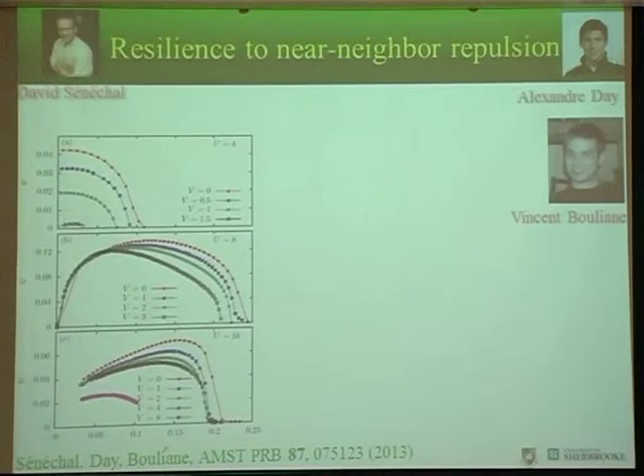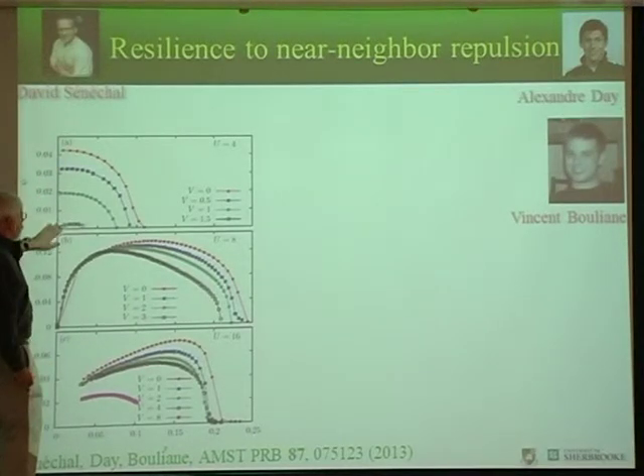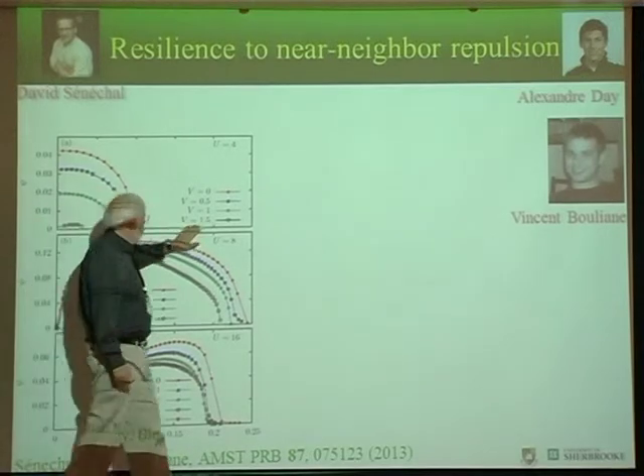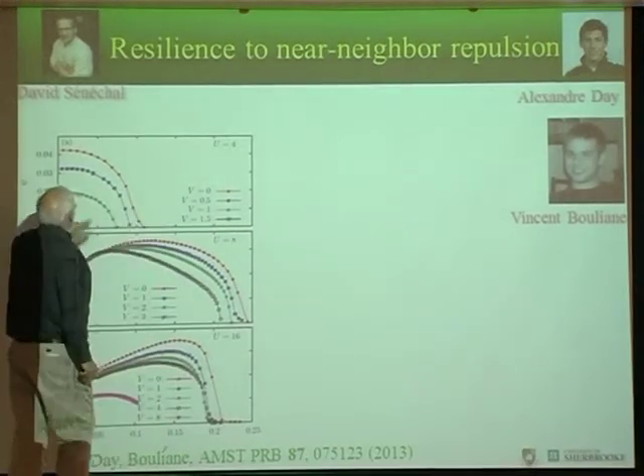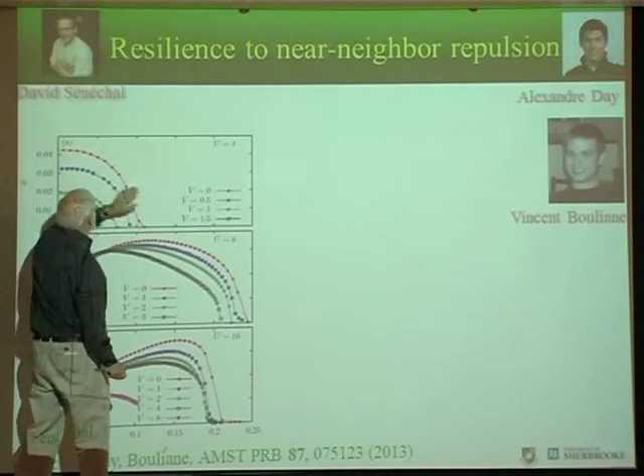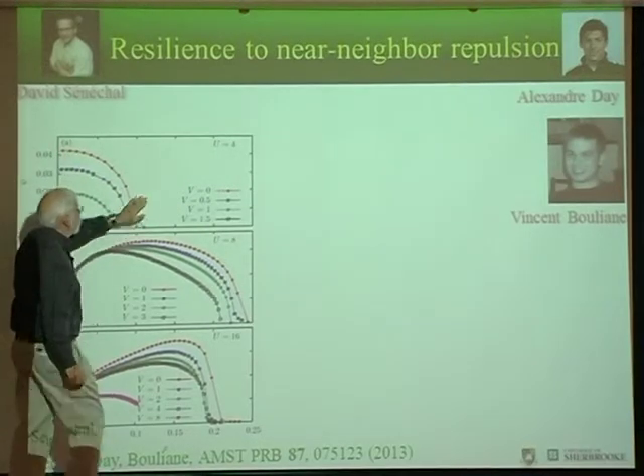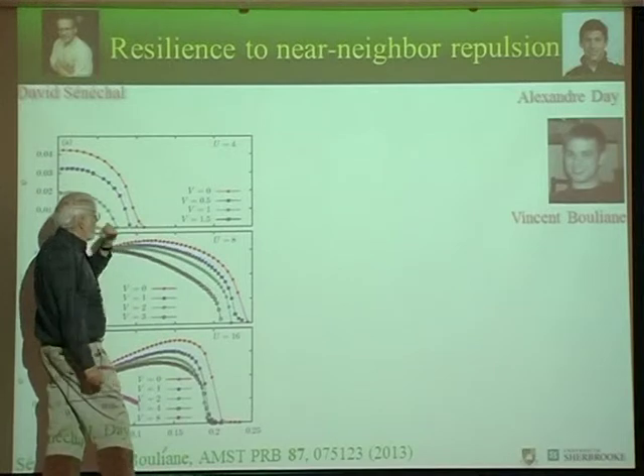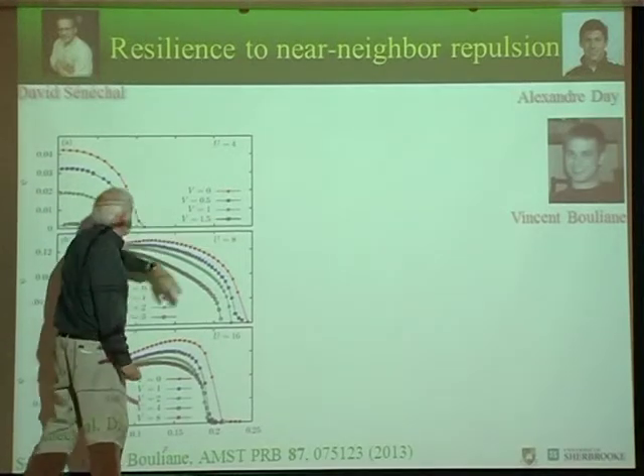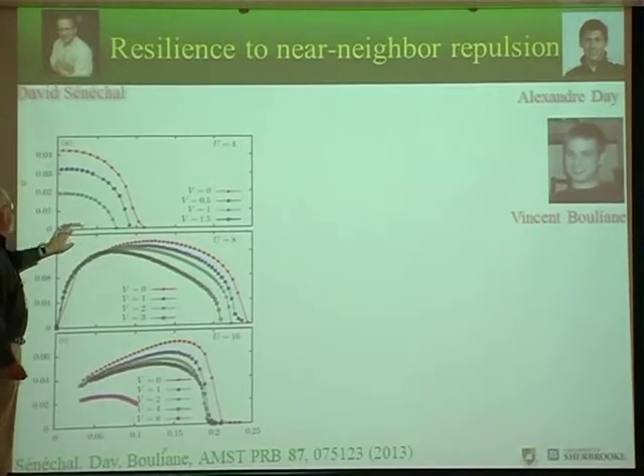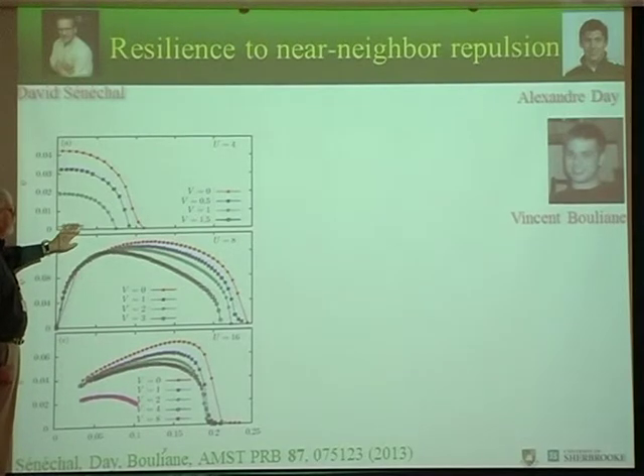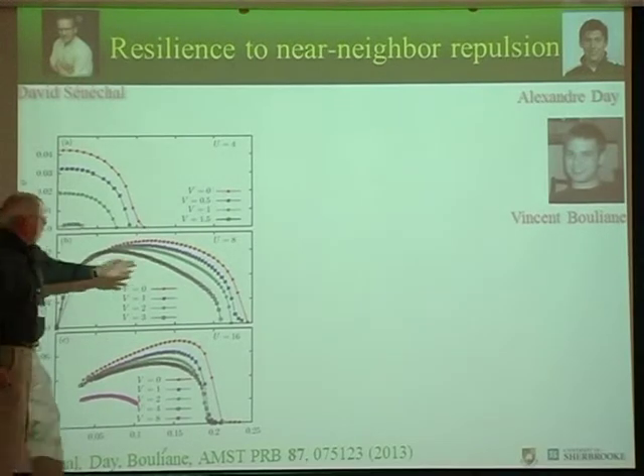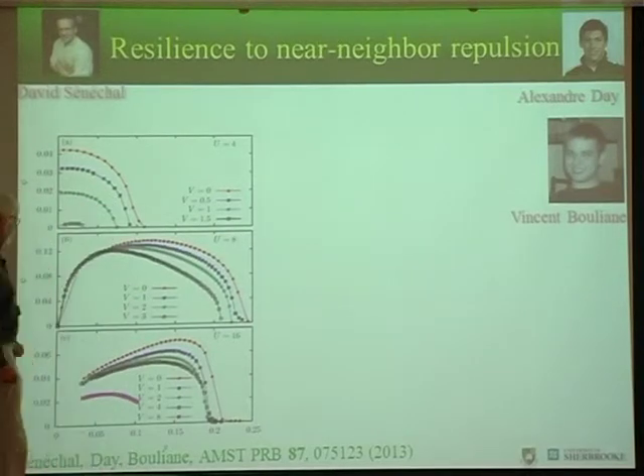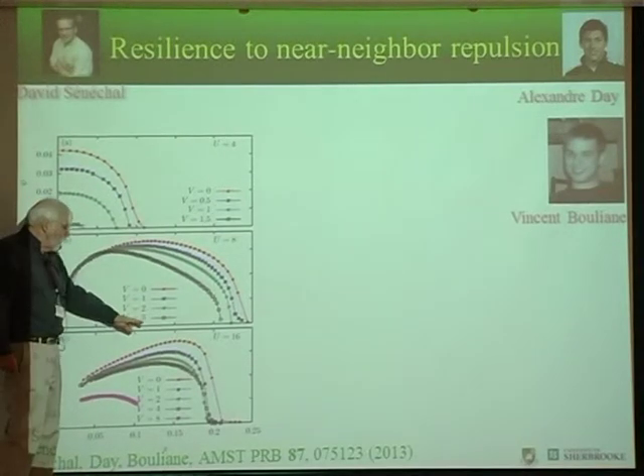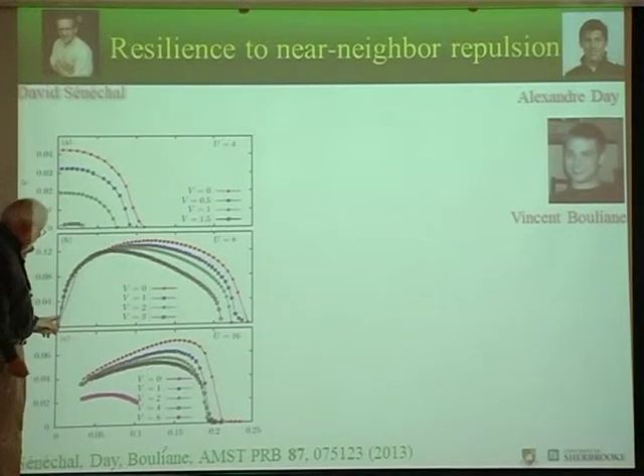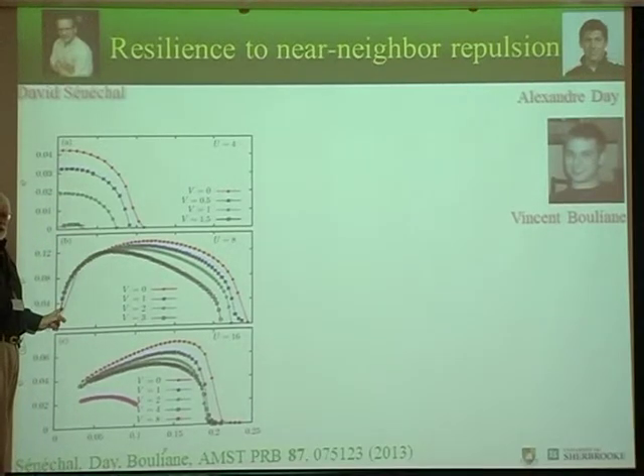Okay, so if we look at weak coupling, this is the order parameter as a function of doping. This is V equals 0, so no near neighbor repulsion. U equals 4, T equals 1. If I go to V equals 1.5, you see that I got rid completely of superconductivity. Now take U equals 8. Now I can go to V equals 3, and nothing has changed here for the order parameter.